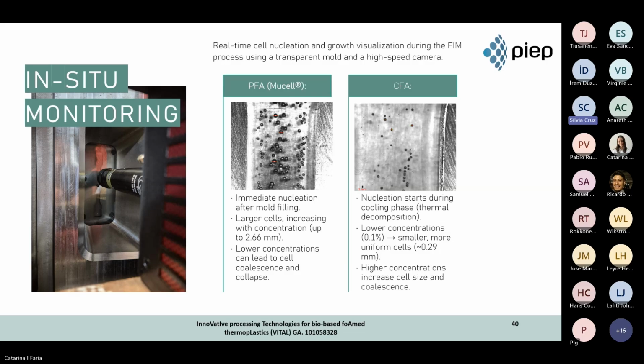Even though this laboratory scale approach cannot be directly implemented at the industrial level due to the use of transparent molds and the low concentrations of foam injection agents required, it is extremely valuable to the development phase of the bio-based material as it provides quantitative data on cell nucleation.